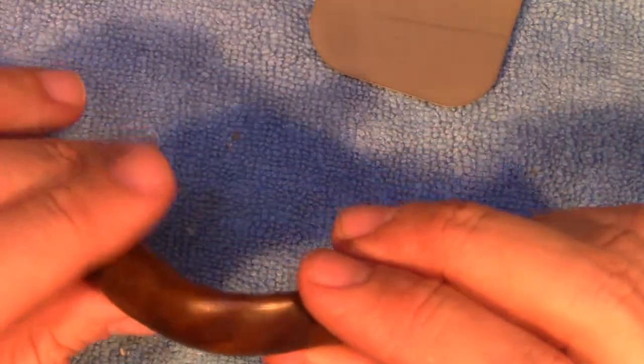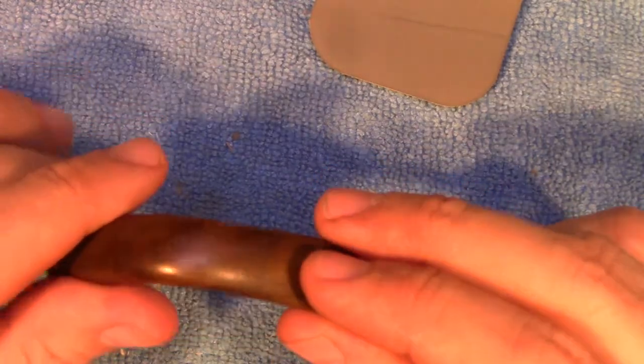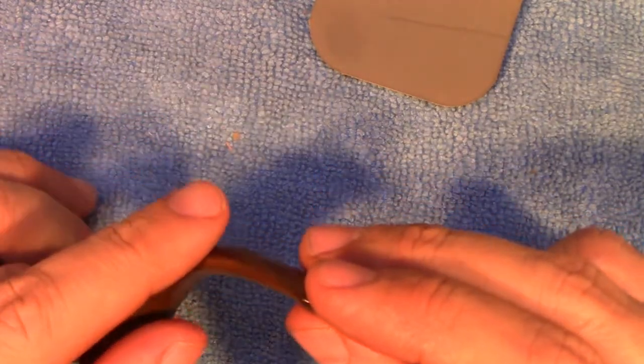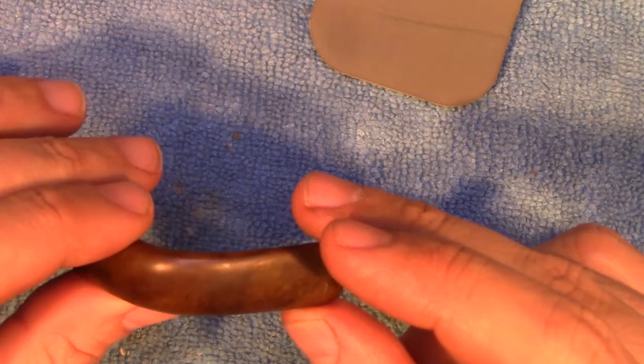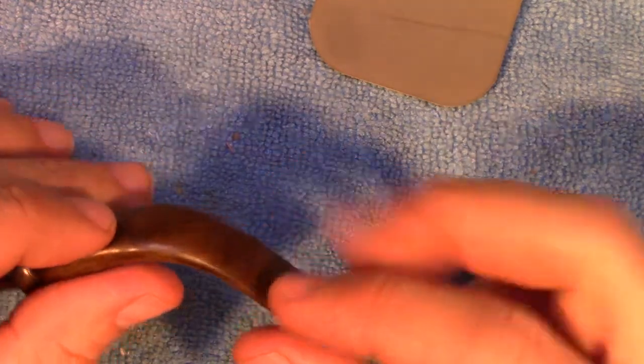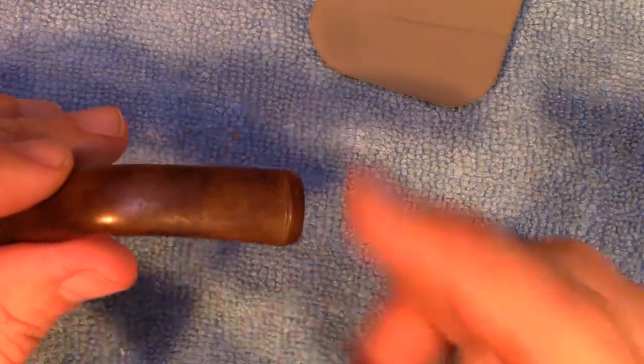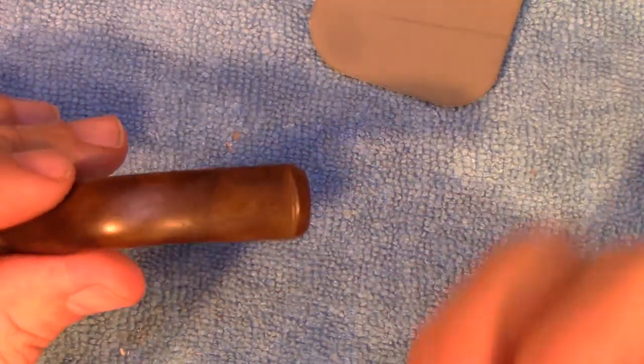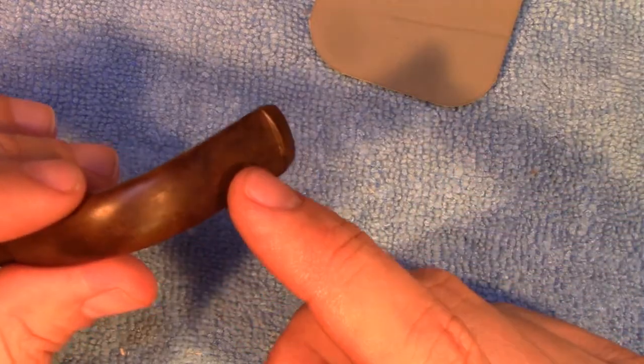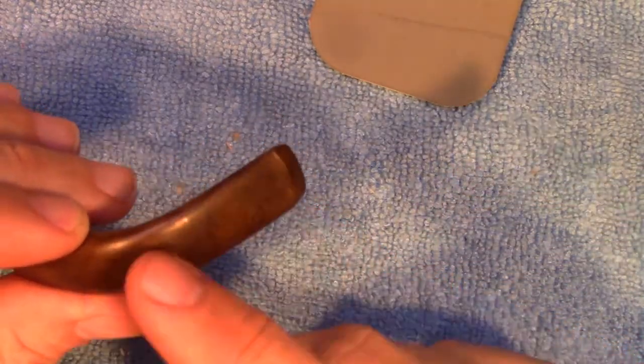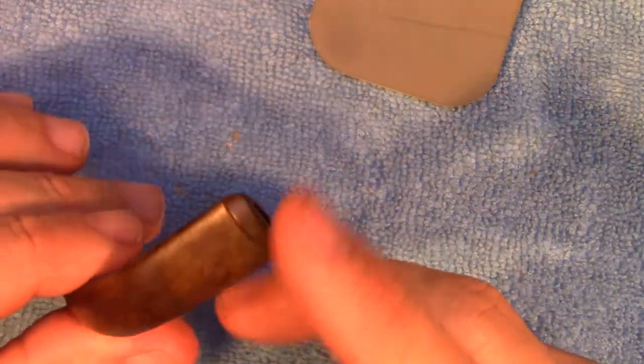This is ebonite and it is oxidized. The oxidation is due to an ultraviolet reaction with the cross-linked sulfur molecules that create sulfuric acid, which when exposed to water or moisture or humidity makes this ugly color appear.